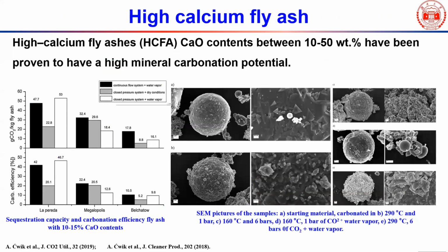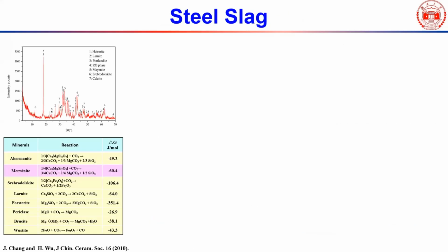In this published result, they said they used high calcium fly ash, but on the other hand, you can see they used a temperature of like 290 or 160 degrees C. So probably that's also why they cannot really get good results at room temperature, right? And yeah.